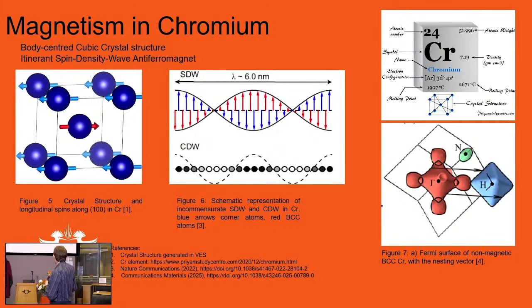Well, firstly, you sit with electron and hole Fermi surfaces, virtual surfaces on which these charges sit in terms of energy. And in chrome, they can actually move relative to each other. But the importance is that the electron one is smaller than the hole. So when they come together, when magnetism forms, one will cancel the other. We call it nesting, in effect. But there always remains a little bit of the surface behind, giving you a positive character to this.